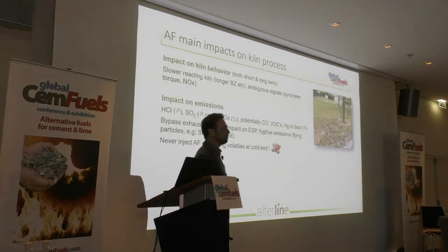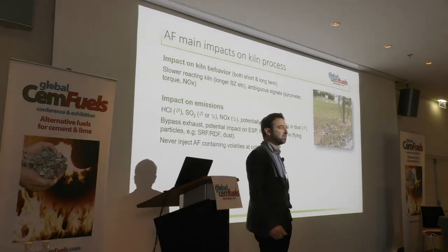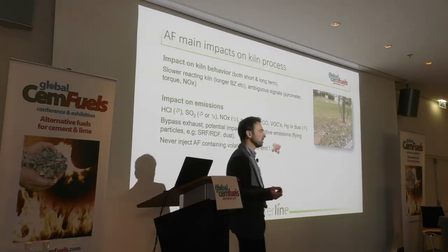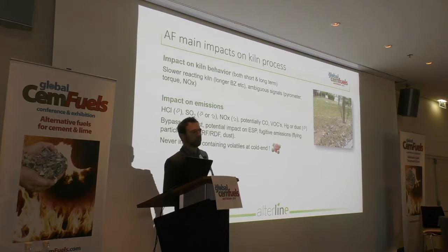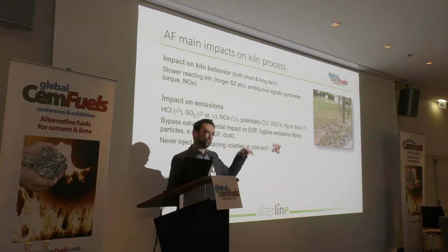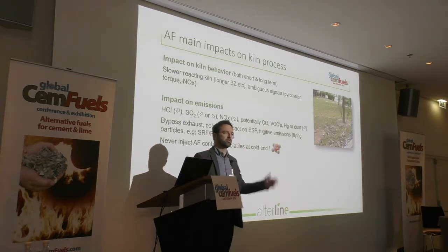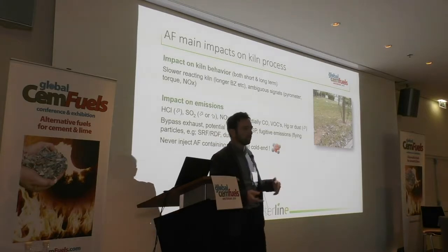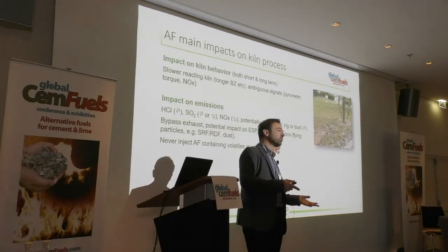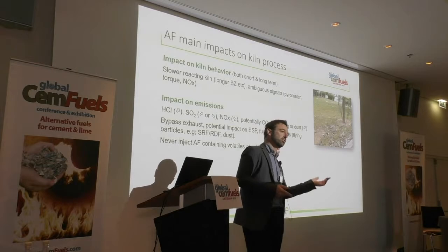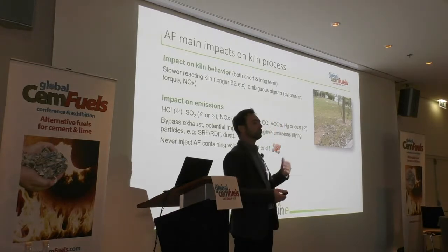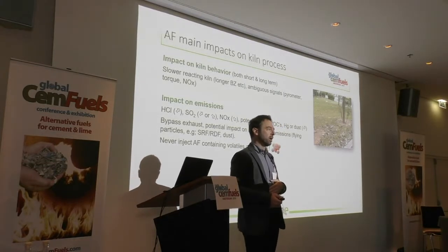The impact on the emissions, typically you can increase or decrease SO2 emission, because if you have big fluctuation, you will have reducing condition from time to time, you will have SO2 peaks, but you can perhaps also improve it by switching from petcoke to alternative fuel. You will reduce the NOx typically.